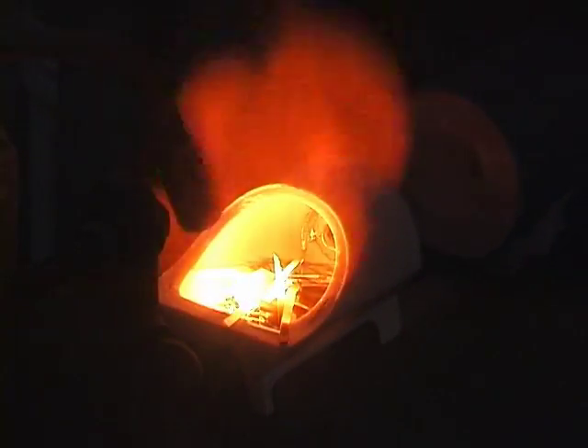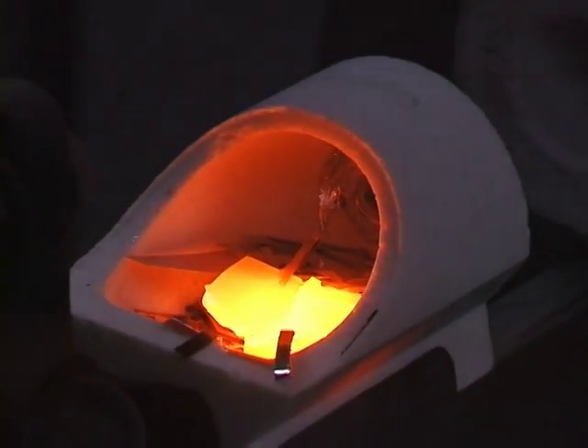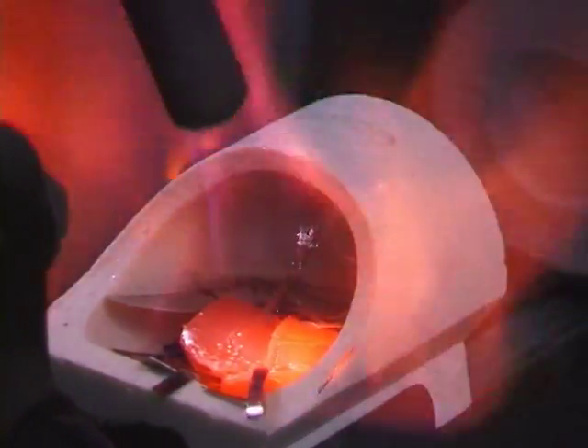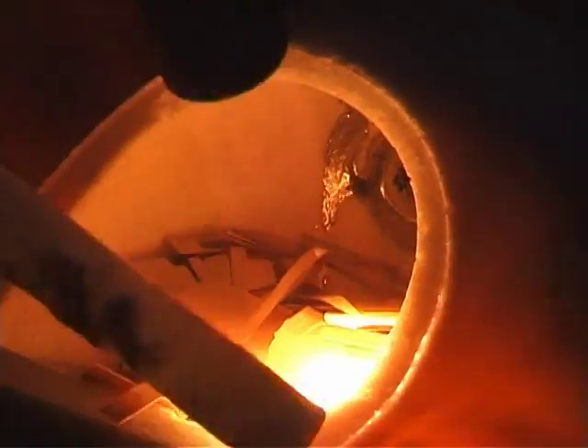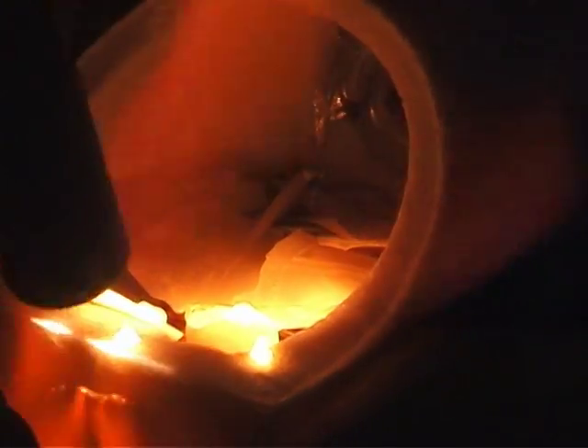The hard cast alloy Greg developed is a nice try, but it's another exotic. When you want to refine it later, you have to deal with the issues. It also oxidizes a little bit — it has a slight gray sheen. So if you want a trouble-free, all-around alloy that you can use for die striking, fabrication, and machining, the choice really is platinum ruthenium.